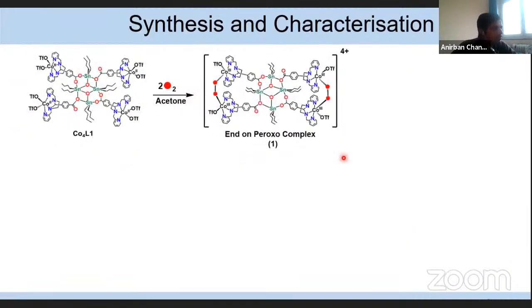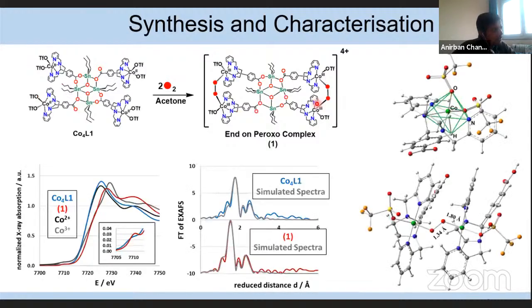Now, to know more about the electronic and geometric structure of the peroxo species that we generated, we did the XAS measurement along with the DFT studies. In the XAS measurement, this figure of cobalt K-edge spectra shows the blue line for the tetranuclear cobalt complex, which exactly matches the reference cobalt(II) complex. So in the starting complex, cobalt is in the +2 oxidation state, whereas the newly generated peroxo species, shown here with the red line, matches exactly with the reference cobalt(III) species. So it is confirmed that all the cobalt centers in the tetranuclear system are oxidized to cobalt(III) upon addition of oxygen. And here you can see the slight increase in the pre-edge shift for the peroxo species, which indicates